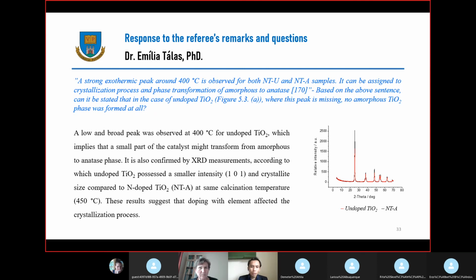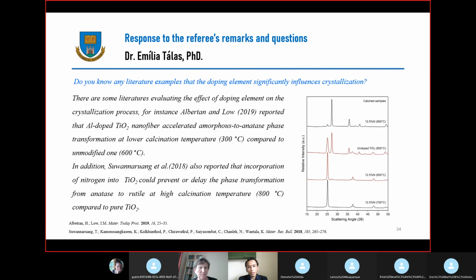Probably the low and broad peak for the undoped titanium dioxide implies that a smaller part of the catalyst may transform from the amorphous to anatase phase. Then if we check the measurement, we try to compare the undoped and the nitrogen doped, we see that the undoped titanium dioxide possesses a smaller intensity in this case, and also a smaller crystallite size compared to the N-TiO2 catalyst at calcination temperature, in this case 450 degrees Celsius. This means that the doping with the element may affect the crystallization process. And also, there is some literature evaluating the effect of the doping element on the crystallization process.